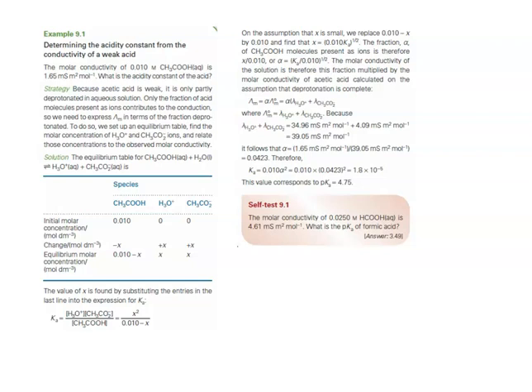The fraction alpha of acetic acid molecules present as ions is therefore x divided by 0.010. The molar conductivity of the solution is therefore this fraction multiplied by the molar conductivity of acetic acid, calculated on the assumption that deprotonation is complete. We can therefore enter the following, where our molar conductivity is going to be determined by the conductivity measurements of the acid and the conjugate base, where we have 34.96 plus 4.09, giving us a total of 39.05.